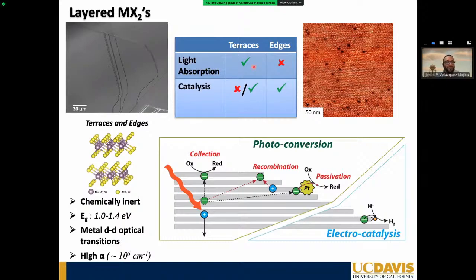And one of the interesting results that we've been able to see thus far is that there's more under-coordination than we thought. The majority of the step edges, in the world of photoelectrochemistry, were the main areas where we think that electron-hole recombination was occurring. Therefore, you would basically lose minority carriers to do photoelectrochemistry. Now it's also happening in the terraces, as I'm showing you here from the scanning tunneling microscopy images. These terraces are also plagued with a lot of sulfur vacancies.